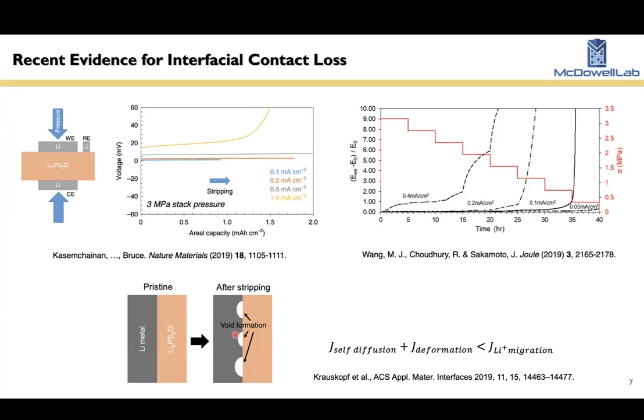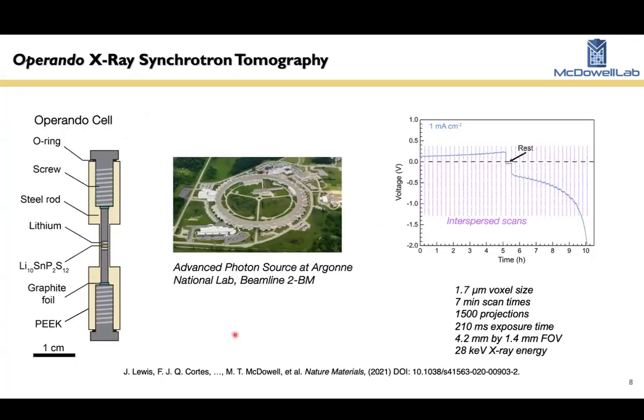So this was predicted based on these electrochemical observations, but what we wanted to do was to see if we could visualize this process using operando characterization. And so we selected operando synchrotron X-ray tomography at a beamline to try to understand this process in more detail. So I'll give you a little bit of information here, since I'll show some other results from tomography experiments throughout the talk. To do these sorts of experiments, we make these specialized custom cells shown here on the left. This is one type we make.